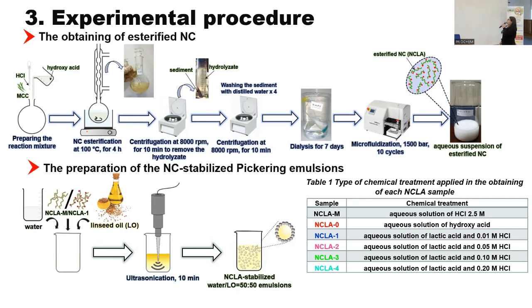We also attempted to add different amounts of hydrochloric acid, because we know that hydrochloric acid can act as catalyst for the esterification of cellulose with different acids, and also hydrochloric acid is believed to be an adjuvant for the defibrillation of nanocellulose during the microfluidization. We can see that we also prepared the control sample obtained by the treatment of microcrystalline cellulose with hydrochloric acid, since hydrochloric acid is a common acid used for obtaining nanocellulose.